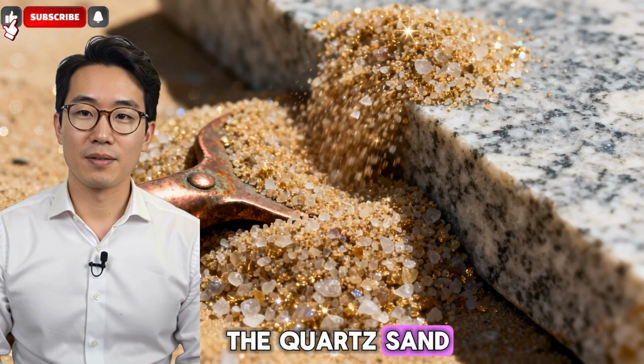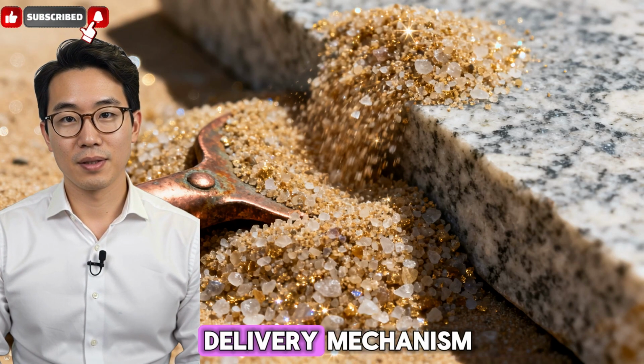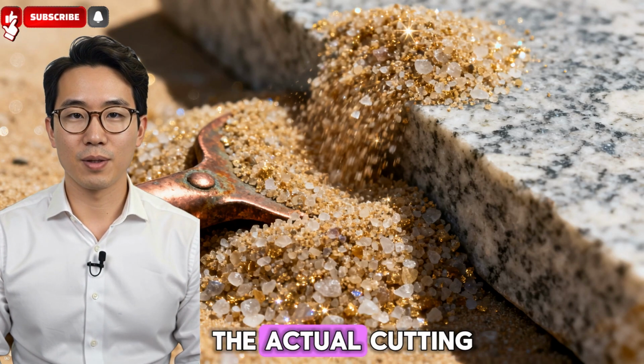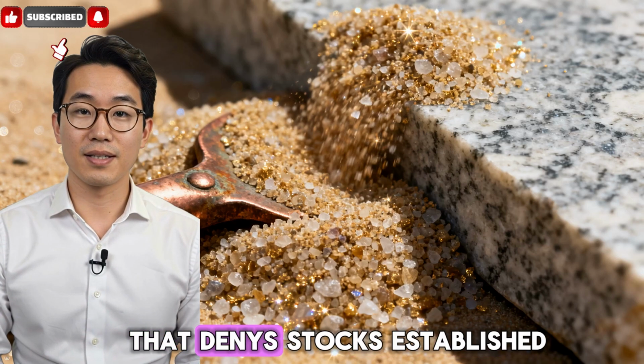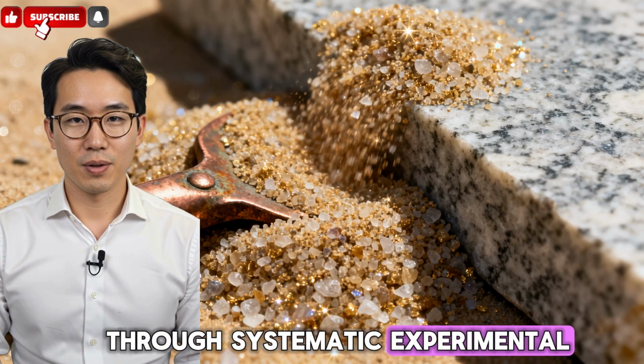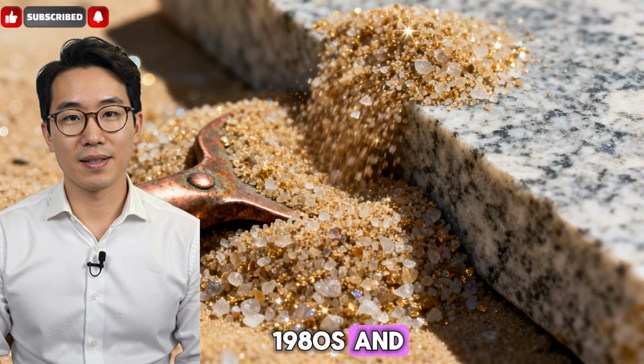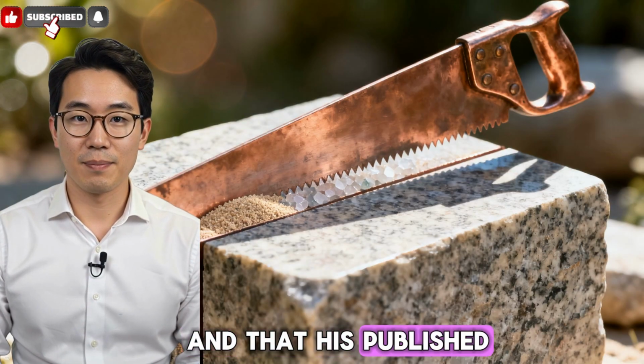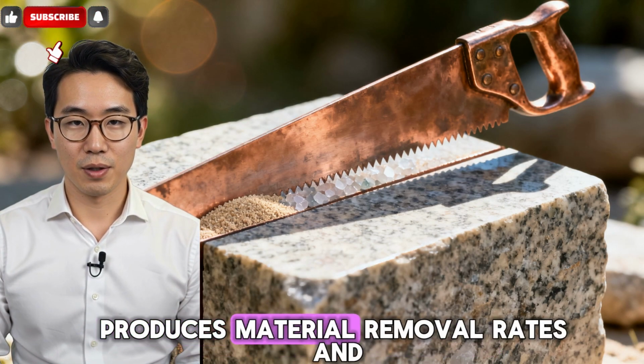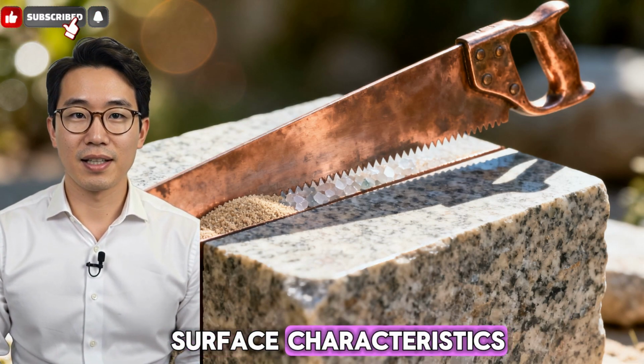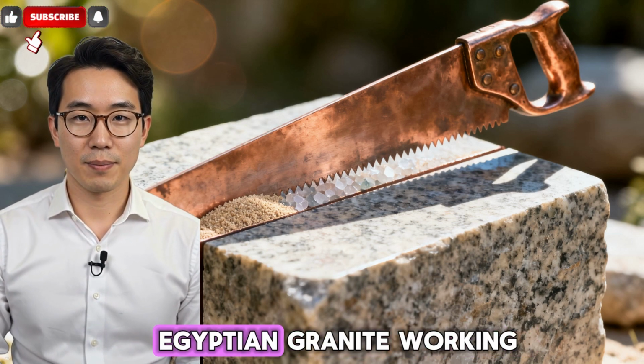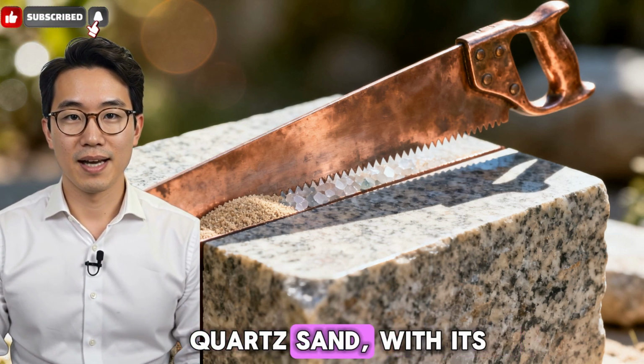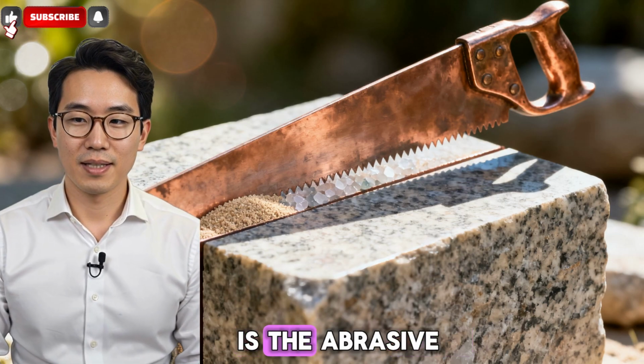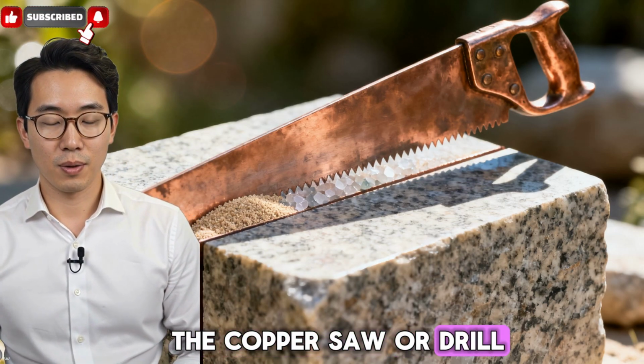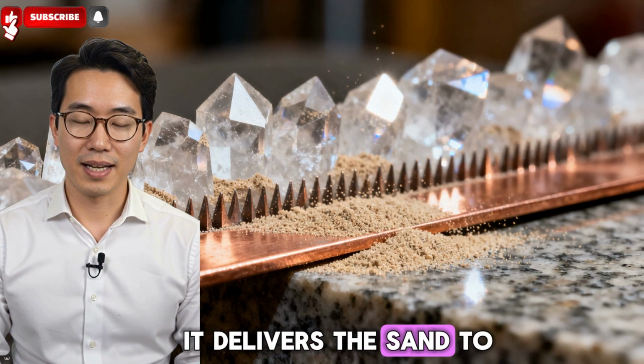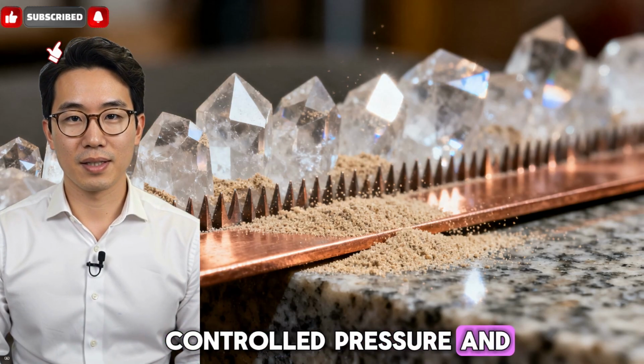The quartz sand, specifically the combination of copper as a delivery mechanism and quartz sand as the actual cutting medium, the mechanism that Denys Stocks established through systematic experimental archaeology across the 1980s and 1990s at Manchester, and that his published experiments confirm produces material removal rates and surface characteristics consistent with most of the surviving evidence from Egyptian granite working. Quartz sand, with its hardness of 7, is the abrasive. The copper saw or drill does not cut the granite. It delivers the sand to the granite surface under controlled pressure and controlled motion.